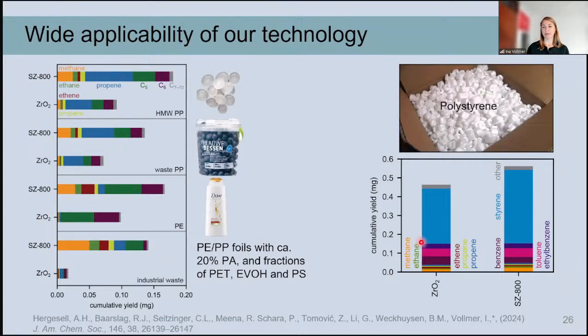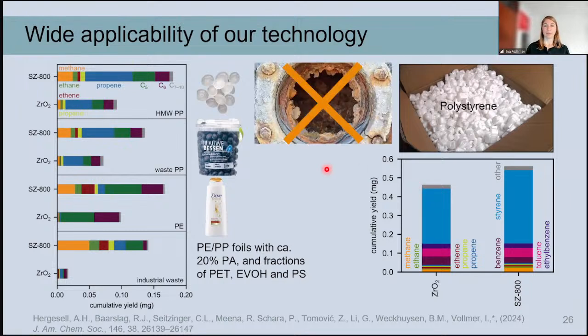And for polystyrene, this depolymerization is generally not as challenging because it depolymerizes more easily also under thermal conditions. But also in this case, we could see that our catalyst has some advantages. And we hope that with our process, we would also have less reactor corrosion because we are working at such low temperatures, and we might form hydrochloric acid from PVC contaminations, but they might not be as corrosive because of the low temperatures that we apply.